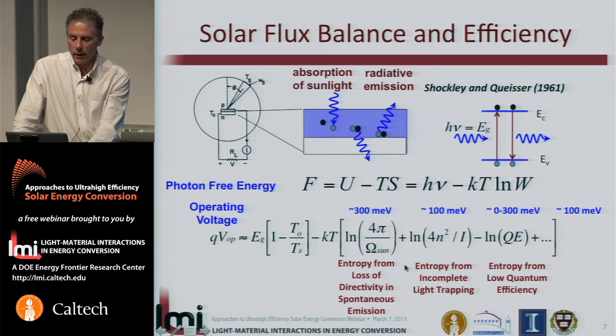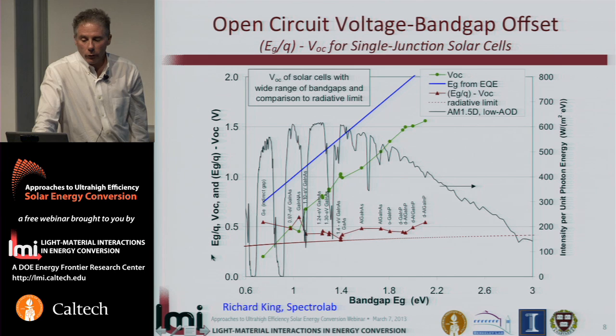There's also an entropy penalty, one can frame this in terms of an entropy penalty, due to incomplete light trapping. And also, if the radiative efficiency of the cell is less than unity, if it's not completely in the radiative limit, then that produces a further loss. And these all translate into losses in the open circuit and then the operating voltage of the solar cell. So this is not only a simple theoretical picture, it's also borne out quite widely in reality.